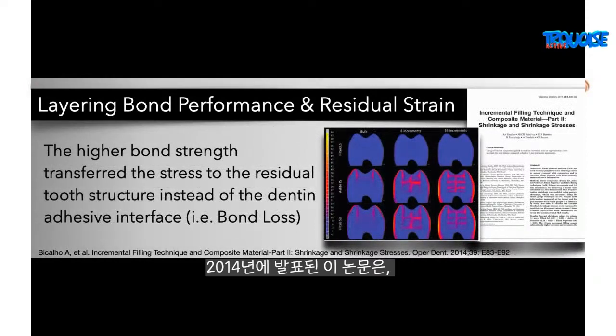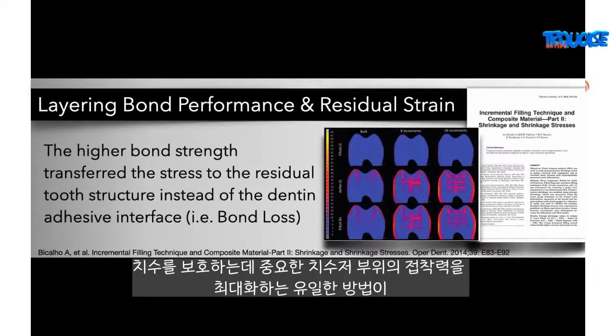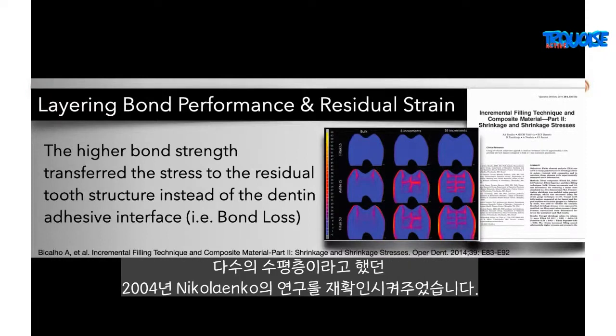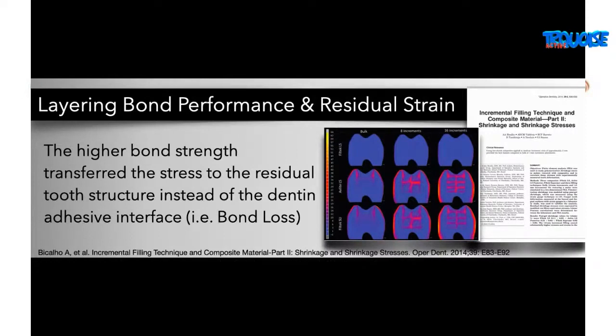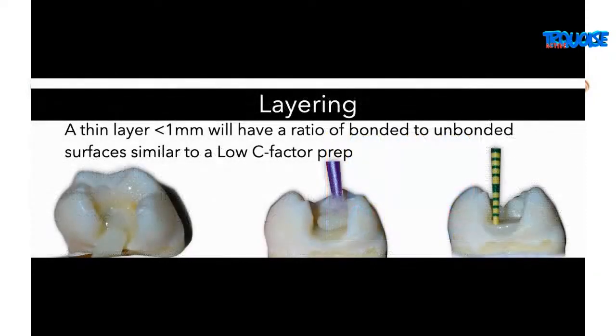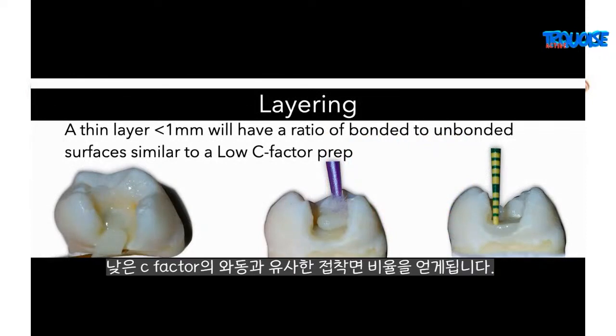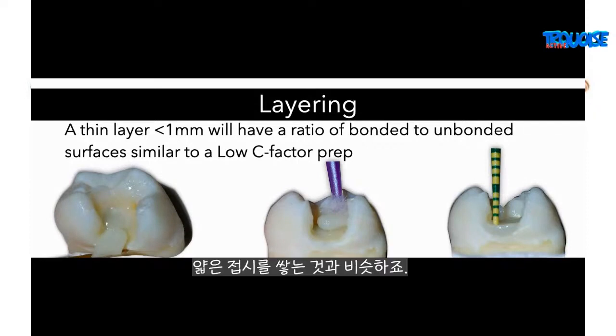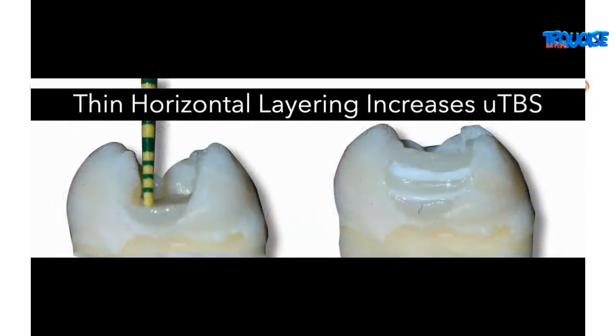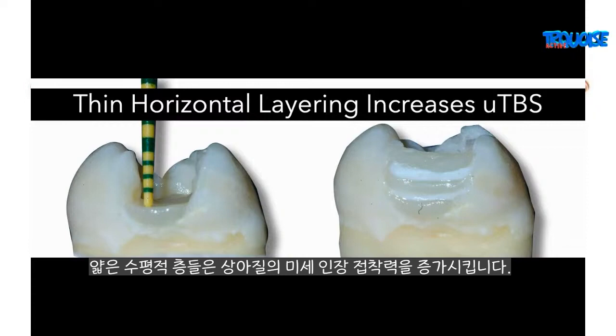And when these studies came out in 2014, it confirmed the study that was done in 2004 by Nikolaenko, saying that multiple thin horizontal layers are the only way to maximize your bond strength in that critical pulpal area of protecting the pulpal floor area. So when we do layering, a thin layer that's less than 1 millimeter will have a ratio of bonded to unbonded surface similar to a low C-factor preparation. So it's like stacking plates, one on top of another. Thin horizontal layering increases the microtensile bond strength in the dentin.